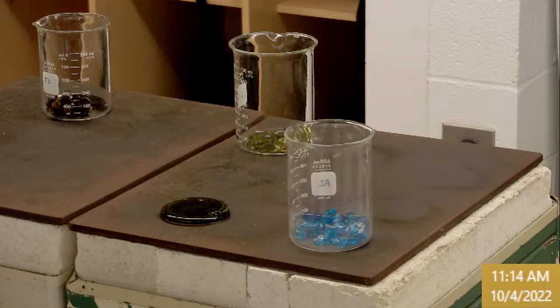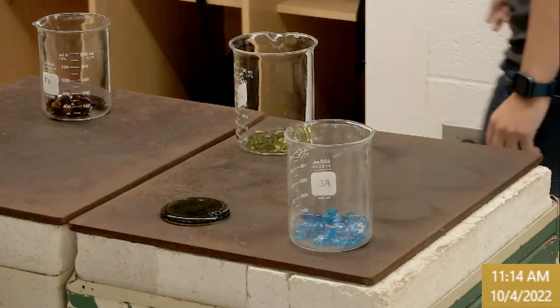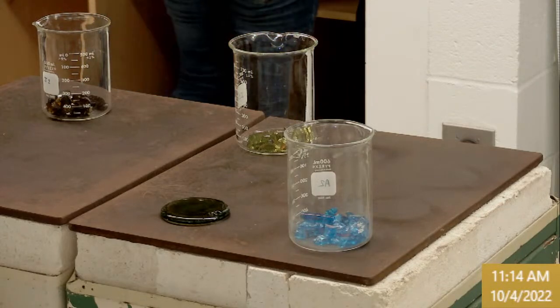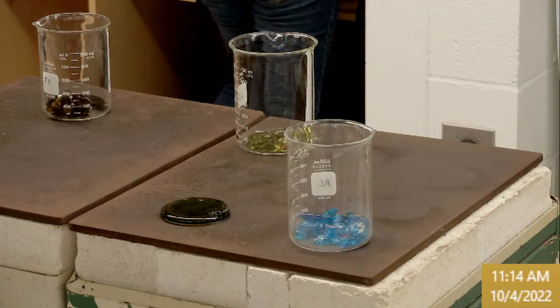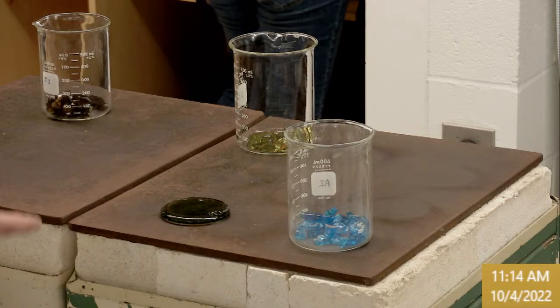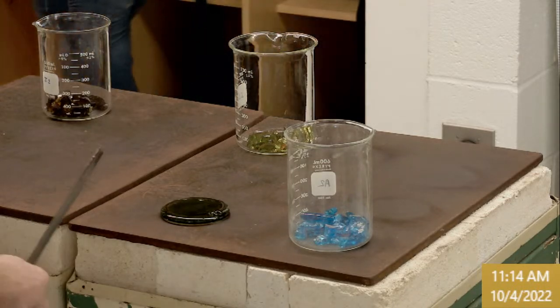So now you can get your pictures of the polarization. Stand above this and look from the top, and what you'll see are bands of color and a gray and white middle area. The qualitative assessment is that the tighter the banding of color, the higher the internal stress field. I'm going to put a little beaker here too. Those have been annealed. If you look at the beaker, all you'll see is gray, and you won't see all those bands of color. We'll add this remaining one once I file off the sharp edge here.